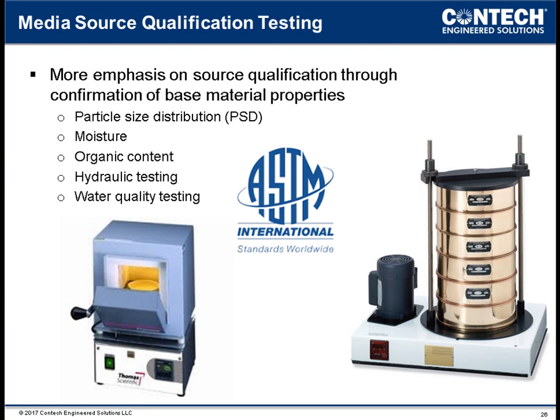Manufacturing QA tests to consider for qualification might include PSD and moisture, organic content, hydraulic testing, and water quality testing. Some others you might want to consider are bulk density, porosity, particle shape, silt and clay content, pH, cation exchange capacity, fertility, soluble salts, leachate tests, even microscopy or toxicity.